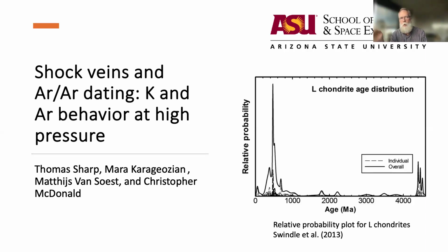The shock wave goes through the sample back and forth and gradually increases the pressure, and this gives you a much cooler sample than if you do it in a single shock, like in a natural shock. One of the main reasons why these shock effects that have high activation energies, like phase transitions, one reason we don't see them in shock experiments is they simply don't get enough energy in shock recovery experiments. If you do an experiment that's not shock recovery, then you can sweep up very fine dust from the bottom of the chamber and analyze it, and very few people do it that way.